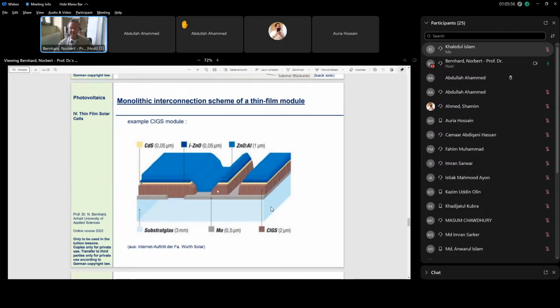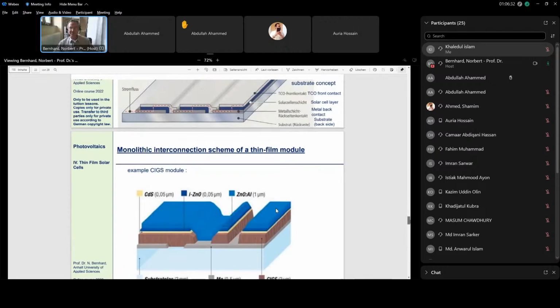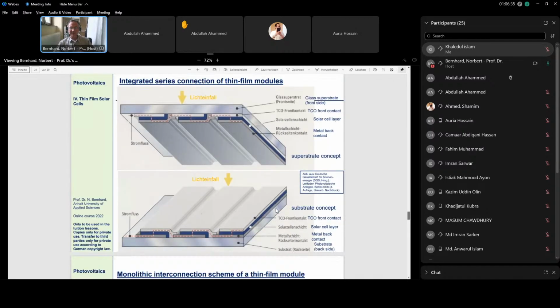That means if one looks at it, one sees there's always a small part of the cell here which is basically not used, because the current path goes from here to here, and this one again. This is just due to the fact that these are typical either laser cuts, this separation, or in the case of copper indium gallium diselenide, the second and the third one are mechanical scribes, and the distance here is just a few tens of micrometers, and this cannot be done so precisely that one can really achieve precisely this form. I mean, the risk for shorts would be too big.